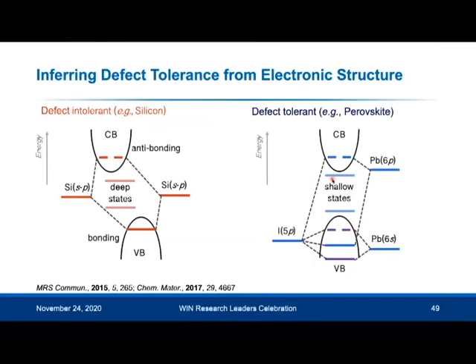And what we know from Shockley-Read-Hall statistics is that the rate of non-radiative recombination depends not just on how many defects you have, but also where the defects are within the band gap. So this is a model for defect tolerance based off the electronic structure.